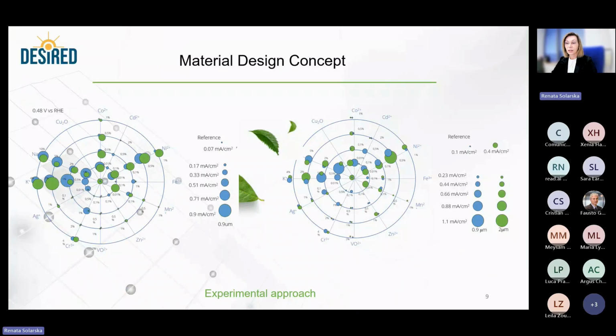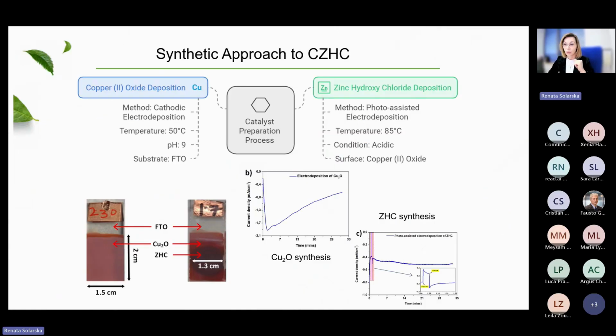And finally, having all the results, we could see which dopants might be the best, regarding not only the structure but also the photoelectrochemical performance, and also the photopotential properties, stability and selectivity. And you can notice on these graphs that, in contrast to Fermi level measurements, the zinc in the bulk is not the best dopant. So that was the reason that